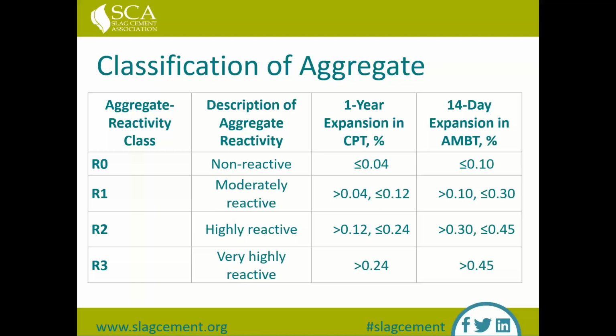It's important to look at both your fine aggregate and your coarse aggregate. If you've got, say, an R0 fine aggregate and an R1 coarse aggregate, you'd want to use whichever aggregate has the higher reactivity class and mitigate to that level. In that case, you'd mitigate to the R1 aggregate reactivity class.